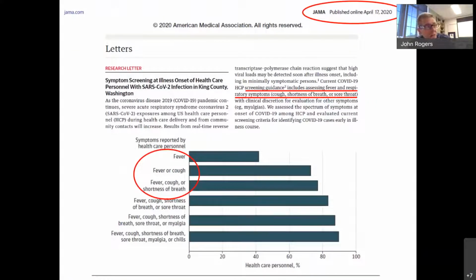So we were engaged with these stroke survivors, deployed at scale through early 2020, and then the pandemic hit, and we began to get quite a bit of inbound requests around the use of our device to track symptoms associated with COVID. And the top 3 symptoms are fever, cough, and shortness of breath. And you can't get any of those parameters very effectively with a traditional wearable because you're not coupled to the respiratory system. You can't even get an accurate temperature measurement from the wrist. But our devices can measure these quantities directly from the suprasternal notch.